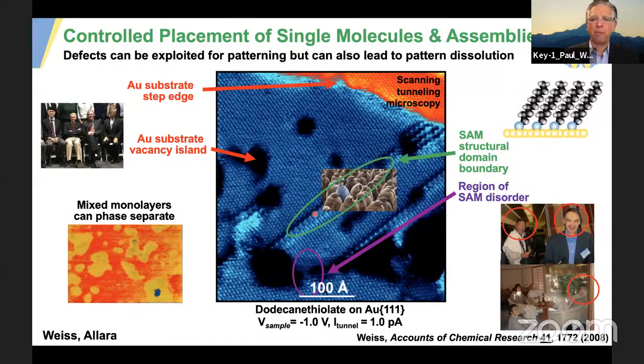So one way that we came into this world was as follows. We had developed a spectroscopic imaging tool in the microwave frequency range to image and record spectra on insulator surfaces. And we're trying to look at as broad a spectrum of materials as possible. And Dave Allara, who's my colleague both at Bell Laboratories and at Penn State, along with Ralph Nuzzo, a colleague at Bell Labs who moved to the University of Illinois, had developed these alkane thiol on gold self-assembled monolayer systems with which most of you are familiar, I'm guessing, where the sulfur is covalently attached to the gold, and the molecules tilt over to form these one-molecule-thick, two-dimensional layers formed from solution, vapor, or contact.